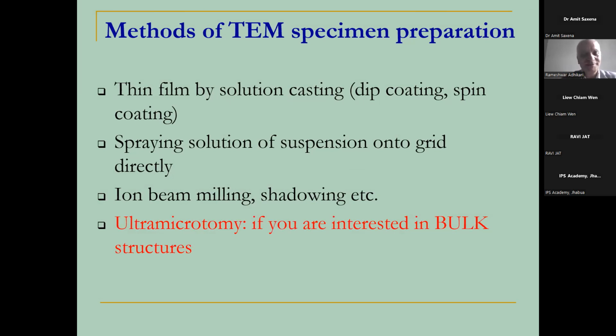For this, there are many methods for sample preparation. The very common method is so-called solution casting. Solution casting is, you have the polymer, you find a suitable solvent. With the help of a suitable solvent, you make a mixture of polymer and pure solvent. We have the solution that could be of different concentration, but generally we use low concentration of the solution.